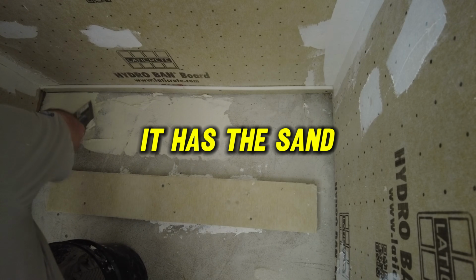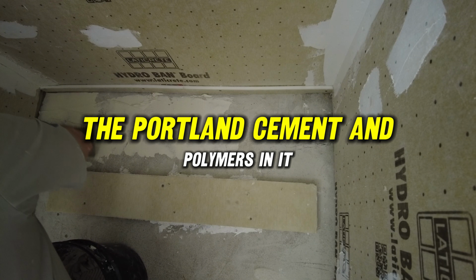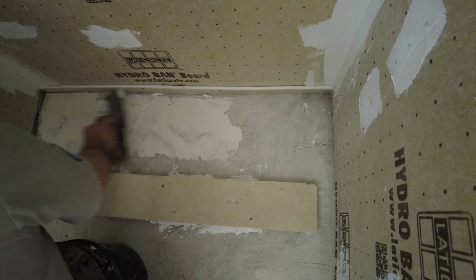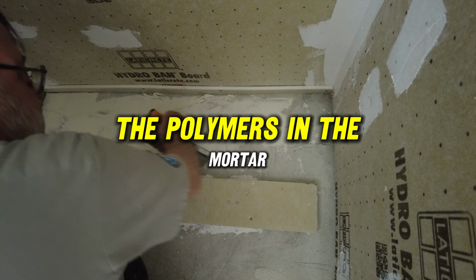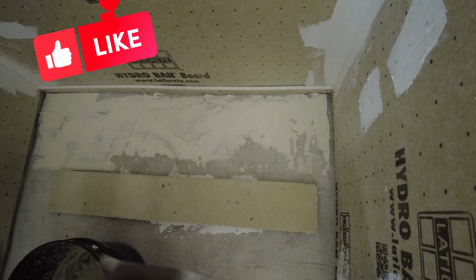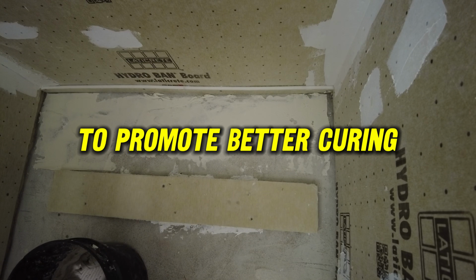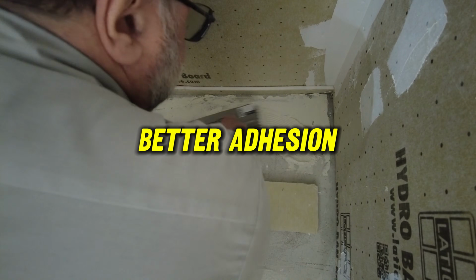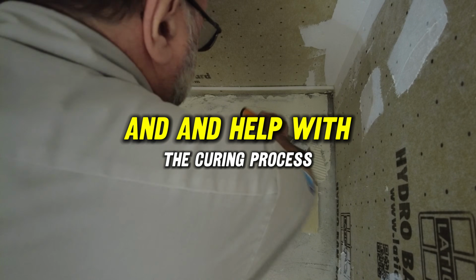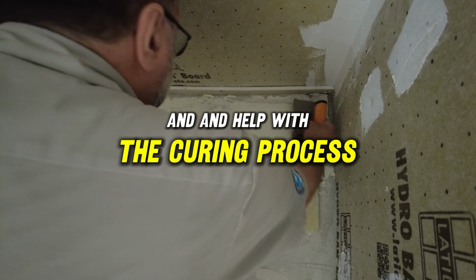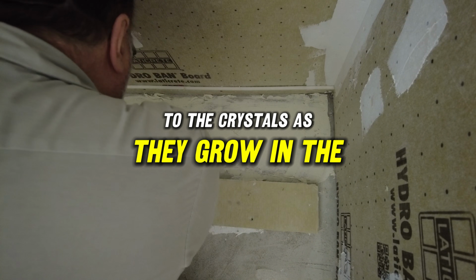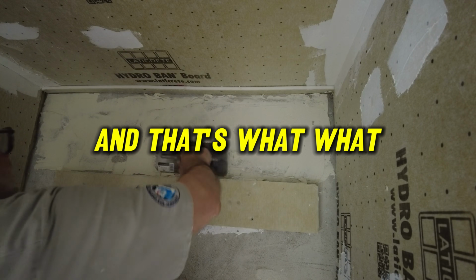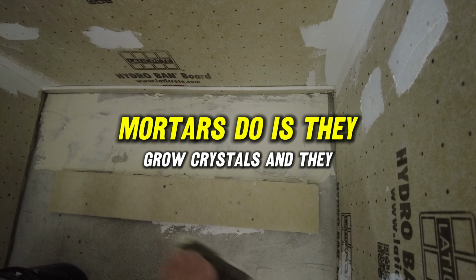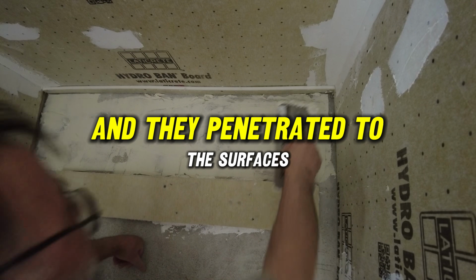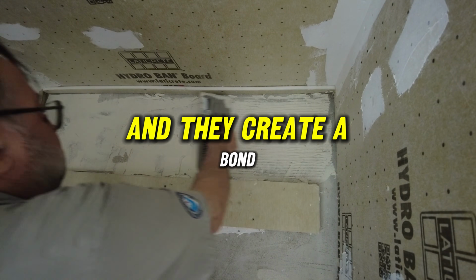Modified thinset has the sand, the Portland cement, and polymers in it. The polymers in the mortar are to promote better curing, better adhesion, and help with the curing process. So the crystals grow in the mortar, and that's what mortars do: they grow crystals and they intertwine and they penetrate into the surfaces and they create a bond.